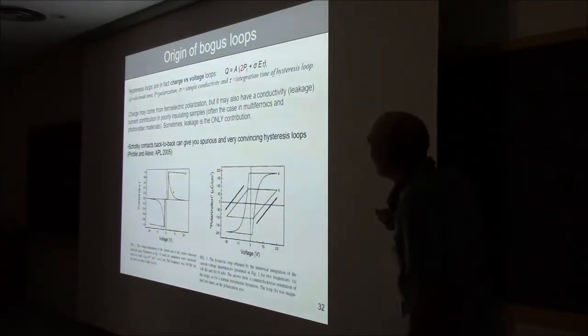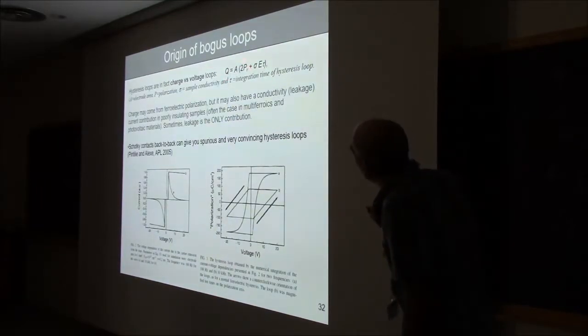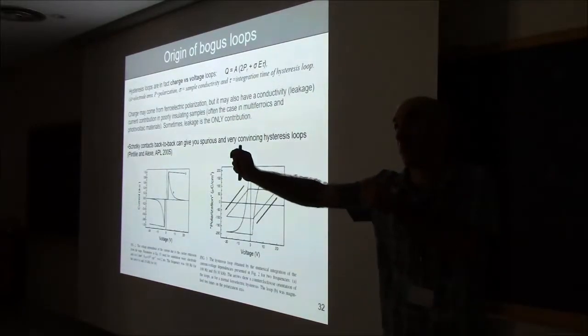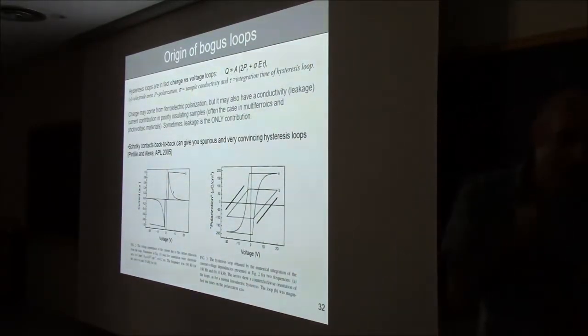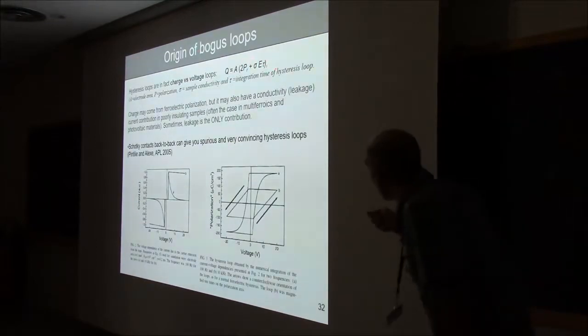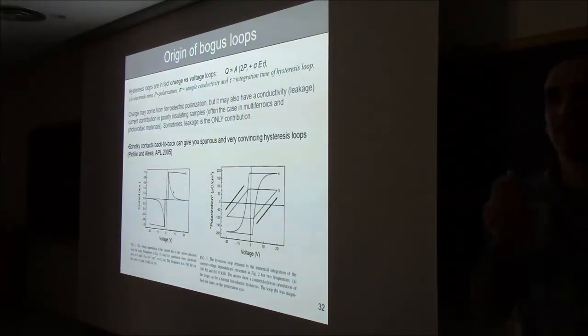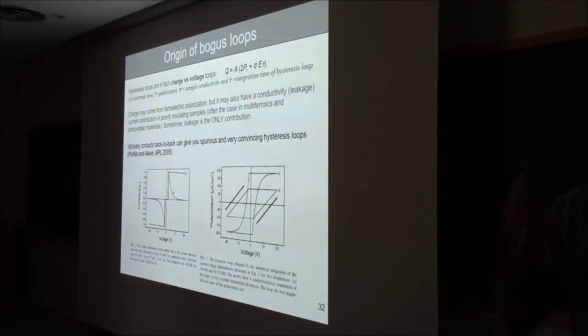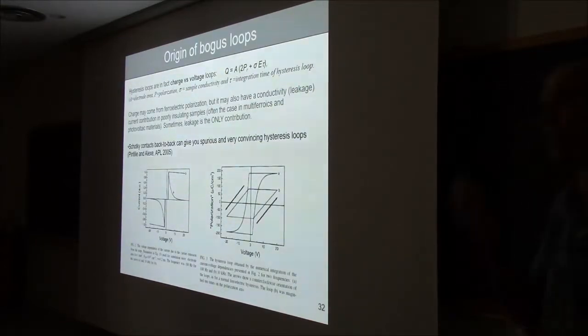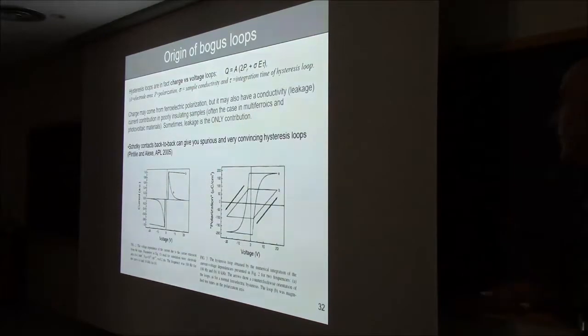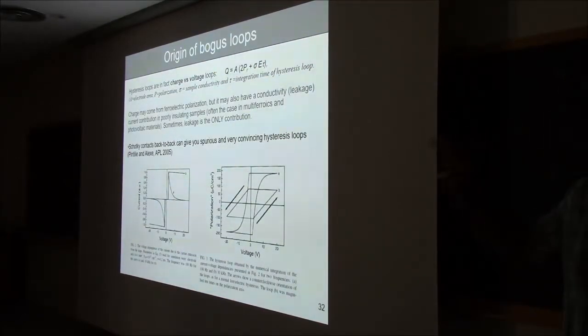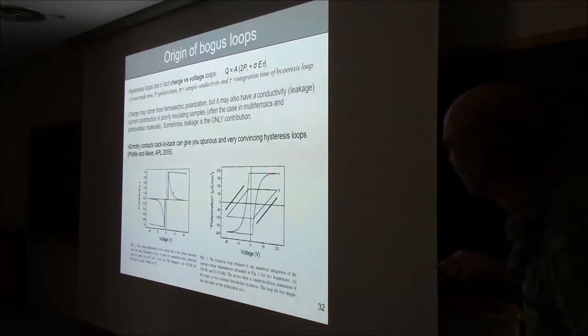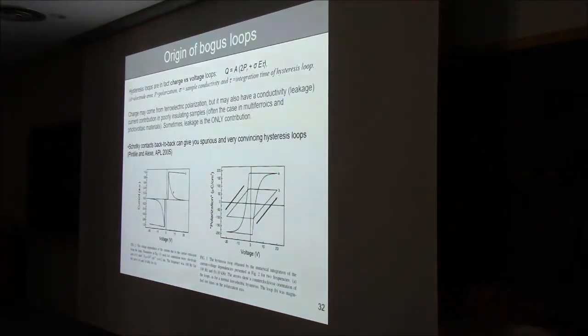Okay, and this comes from the fact that when you measure charge, you can measure charge that comes from the switching of this polarization, but you can also measure charge that comes from the conductivity times the electric field times the integration time. Okay, and I have to stress this effect can be very misleading, can be very deceptive. It can look like real hysteresis. If you do the theoretical hysteresis curve for two pure Schottky diodes back to back, this is what you should get. Okay? And this does look a lot like a ferroelectric hysteresis loop.